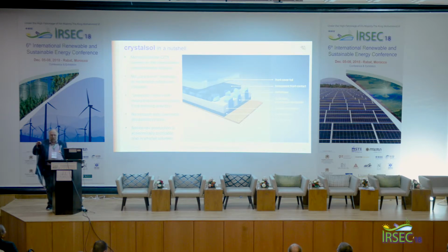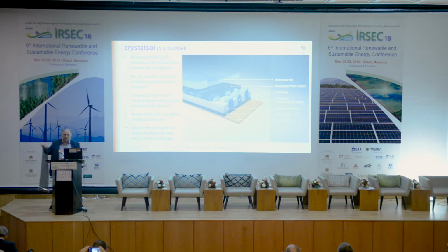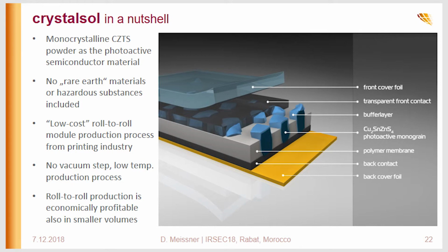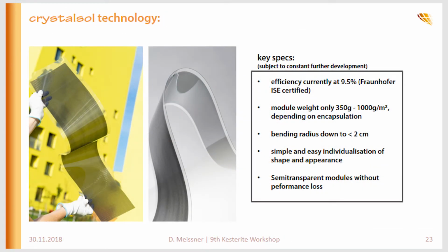All these powder particles, which you see in this little box, are sitting side by side. They touch each other, but there is no conductivity within the film, so every particle actually is a separate solar cell. Okay, it already has a PN junction because we protect the surface of the CZTS, which we grow, with a buffer layer, which can contain cadmium or cannot contain cadmium. Still, the cadmium-containing buffer layers are about 10% better than the ones without cadmium, but both work, actually. And you have these transparent modules, which currently have an efficiency up to 9.5% in a cell.